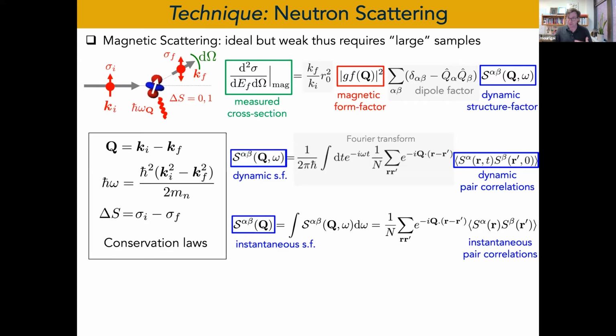when we start looking at material, sometimes we integrate over energy and we calculate the instantaneous structure factor, which is a reflection of instantaneous correlations in the system. So that quantity is a three-dimensional object, which sometimes is easier to analyze when we start on new materials. So in my talk, I will present plots, which are essentially plots of the dynamic structure factor, or the instantaneous structure factor, S of Q.